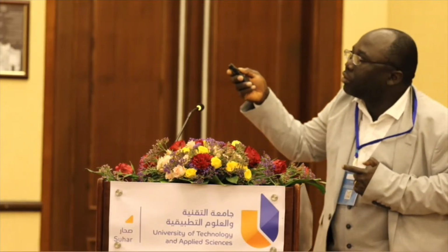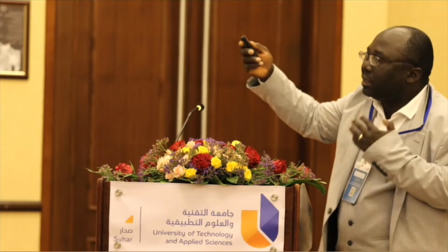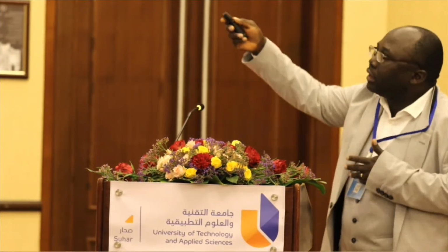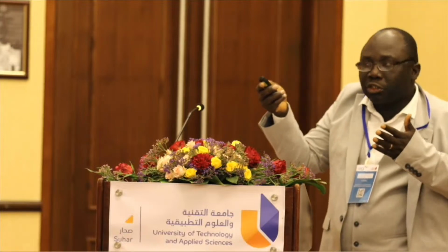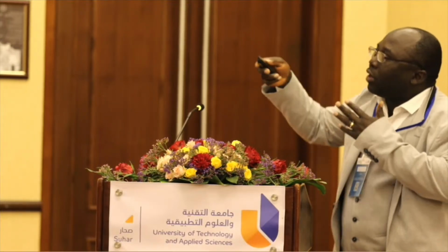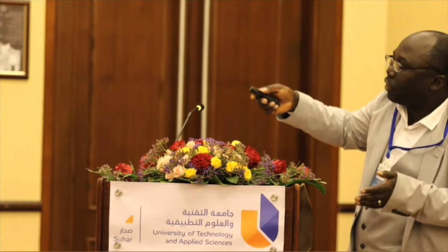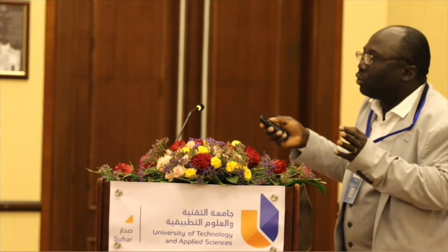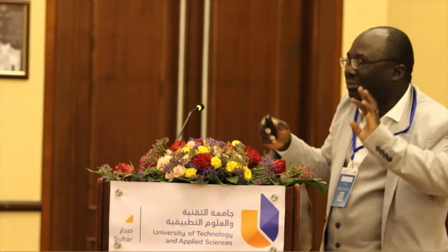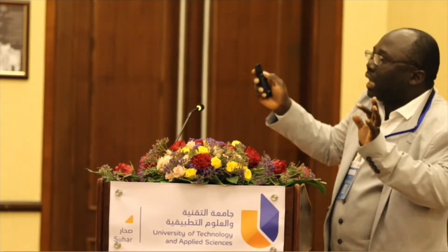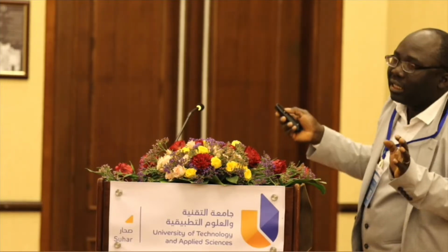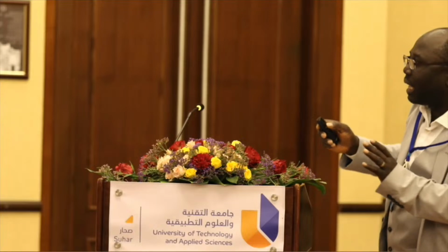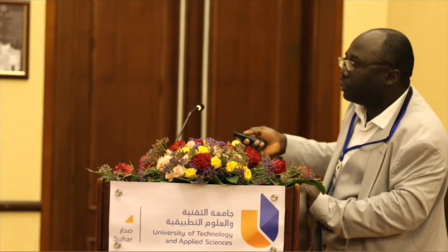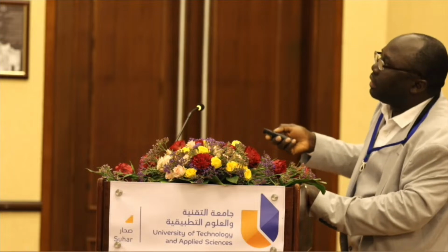Okay? Then we also looked at different technologies that can be used to make this happen. We did some assessment, looked at what has been done already on electrochemical decomposition method. We also looked at photocatalytic routes, and each of them has its limitations. The electrochemical decomposition method uses very expensive catalysts, and we didn't want to go there. We looked at the photocatalytic route. Based on state-of-the-art catalyst, the conversion that can be achieved with photocatalytic cracking is extremely low.